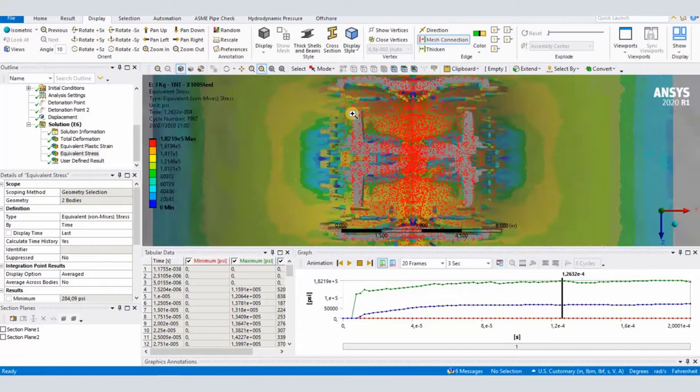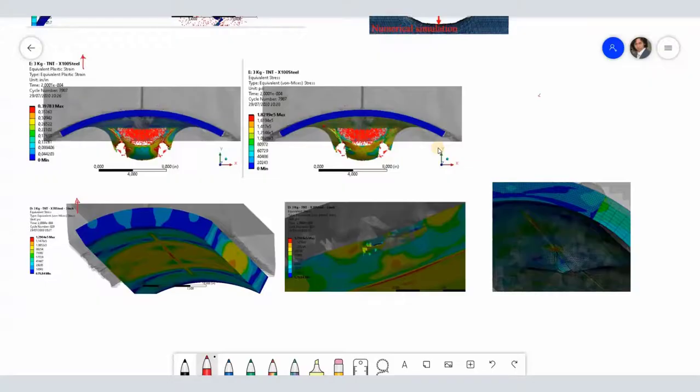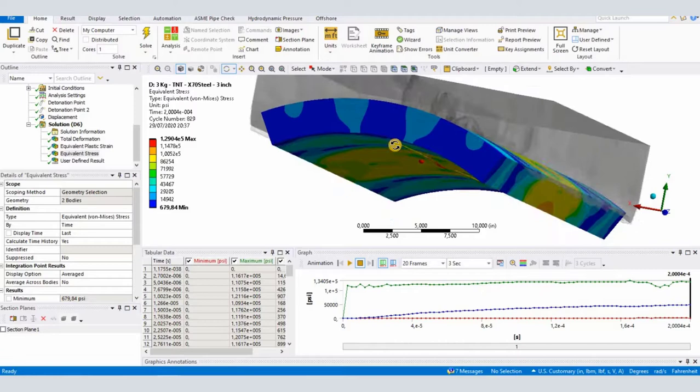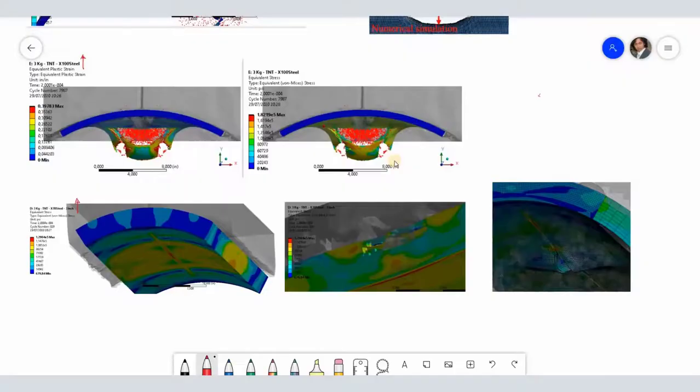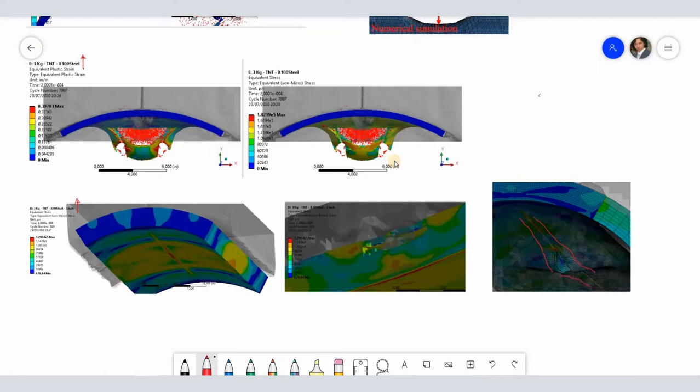Lastly, we have the simulation related to a thick pipe, three inches of thickness. This pipe that we see here and this line is the first state of cracking of the pipeline at longitudinal axis. This screenshot at the right shows us a more advanced state of failure from the same pipe, where we see a cracking virtual fracture and some elements eroded at the center where the highest stresses are found because of the three-axial stress state.